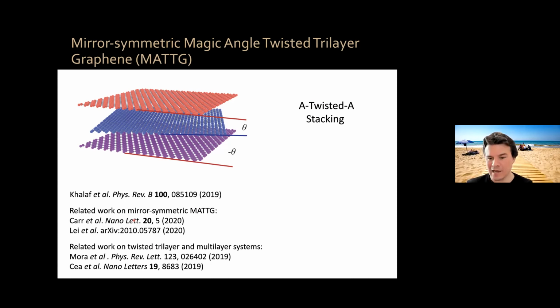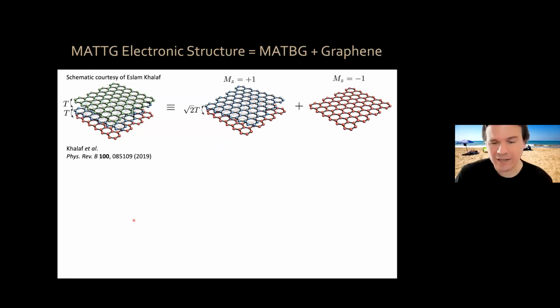Now, one thing that is very interesting is that for the electronic structure of the system, you can think of these three layers as magic angle bilayer graphene plus monolayer graphene. It turns out there is a linear combination of the orbitals in these three layers. The symmetric one gives you a magic angle twisted bilayer graphene-like system with, interestingly, a square root of 2 larger interlayer tunneling. And then the anti-symmetric combination gives you a monolayer graphene-like band structure.